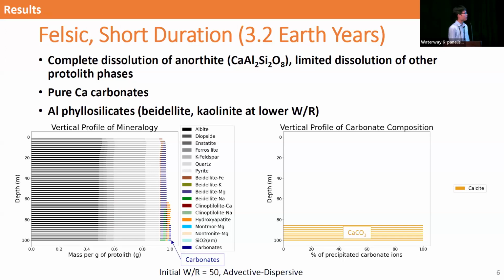Next, we look at the felsic protolith, starting with the short duration of alteration. Of the protolith phases, anorthite completely dissolved, and there was limited dissolution for other protolith phases. And the resulting carbonate composition was pure calcium carbonate, and they're associated mostly with aluminum phyllosilicates.